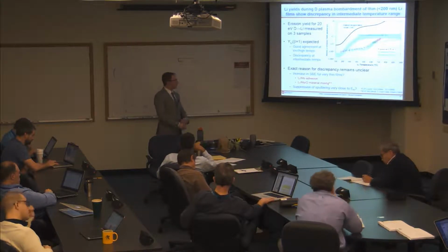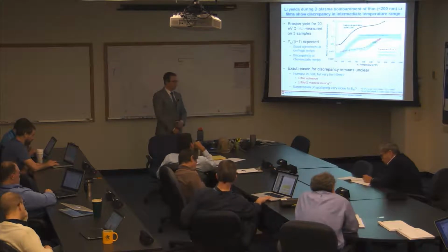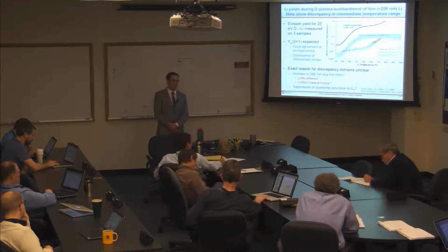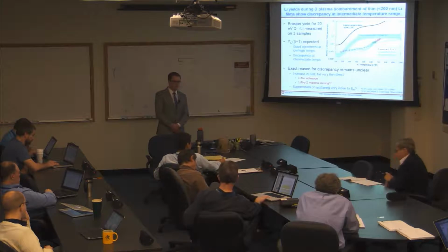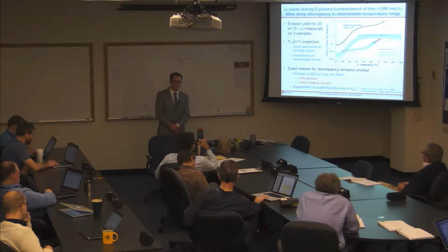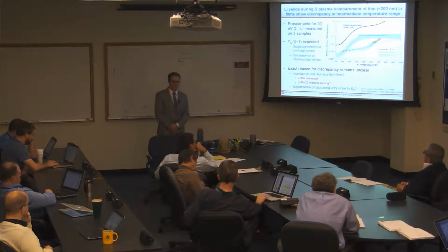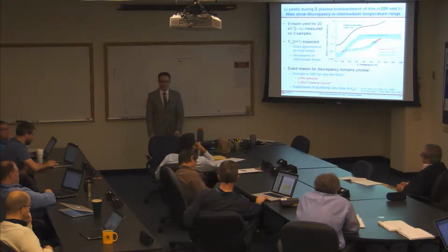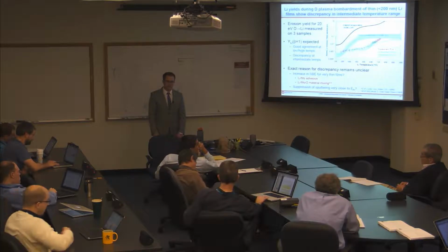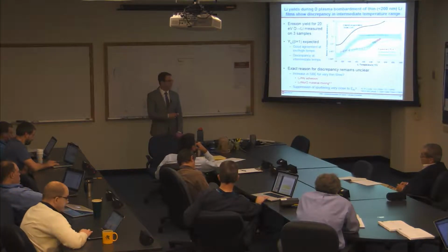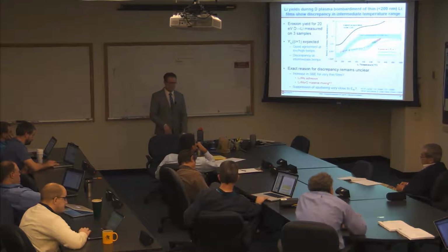The bottom line is that only the first few monolayers, or maybe the first 10 or 20 nanometers, matter in the context of erosion. So what's going on underneath is unimportant until the layer is actually depleted to where it shows through. So in time, there's just that first millisecond where these conditions get initiated, and then it's pretty much right from then on. Yeah, in this very thin case, or that's the prediction at least.